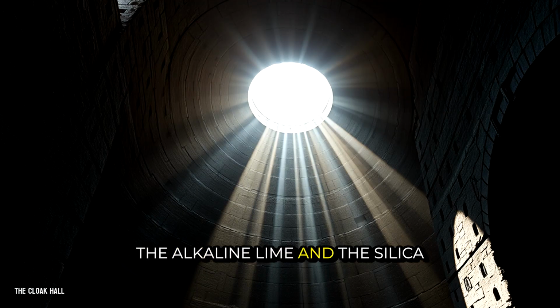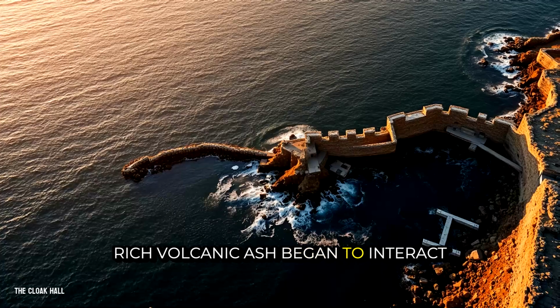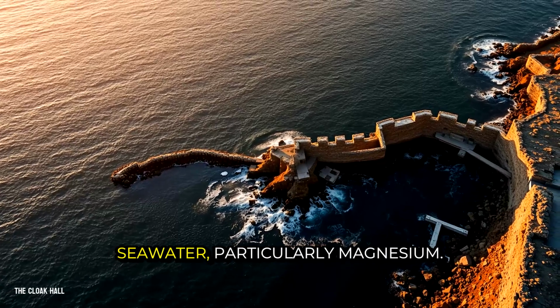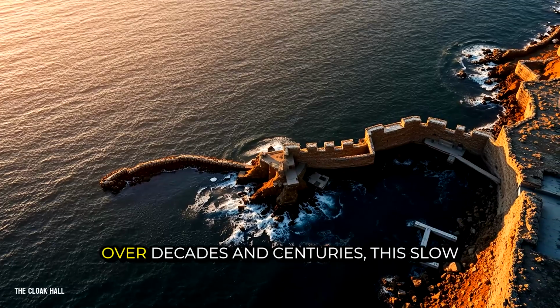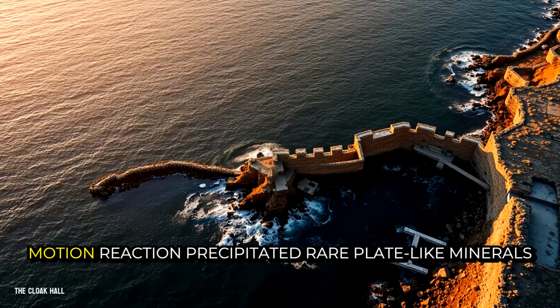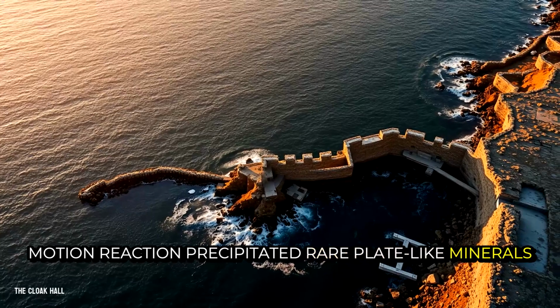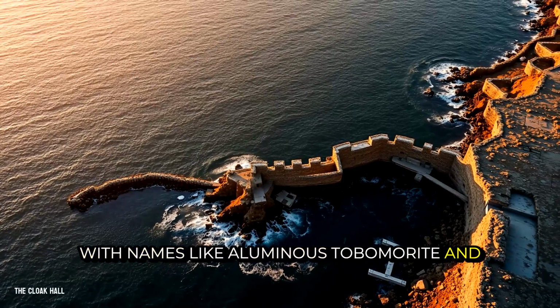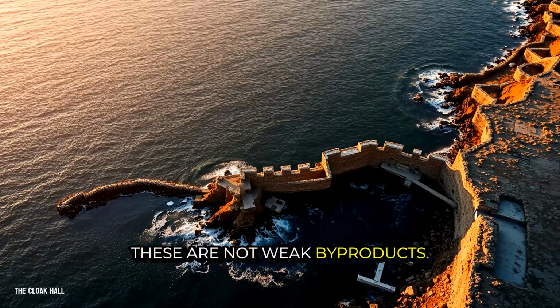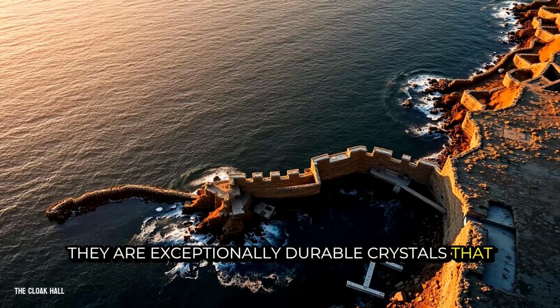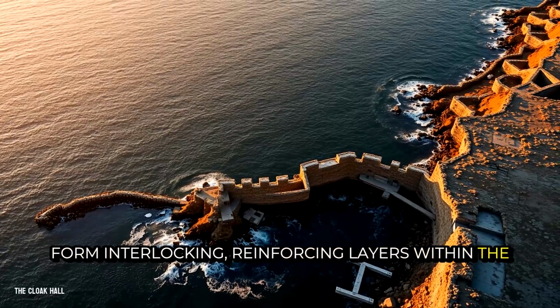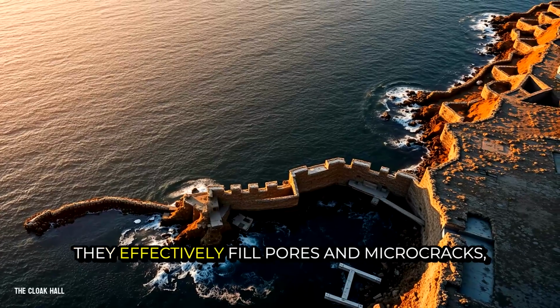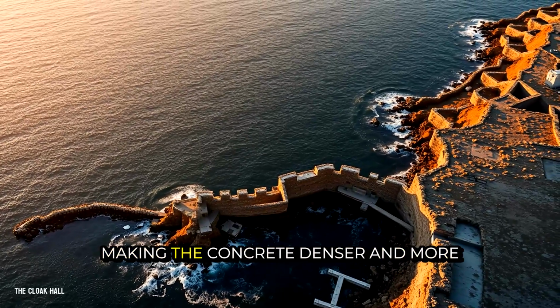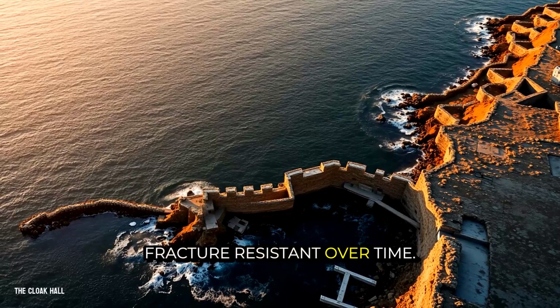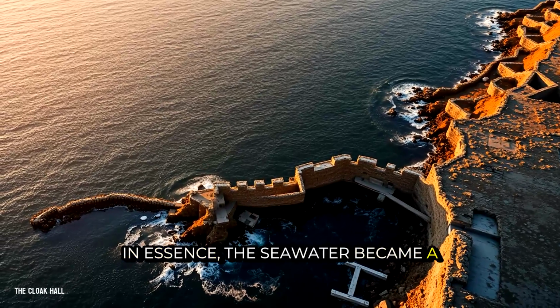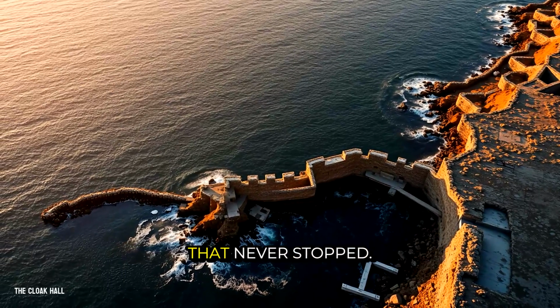The alkaline lime and the silica-rich volcanic ash began to interact with the dissolved minerals in the seawater, particularly magnesium. Over decades and centuries, this slow-motion reaction precipitated rare, plate-like minerals with names like aluminous tobermorite and philipsite. These are not weak byproducts, they are exceptionally durable crystals that form interlocking, reinforcing layers within the material's fabric. They effectively fill pores and microcracks, making the concrete denser and more fracture-resistant over time. In essence, the seawater became a key ingredient in a curing process that never stopped.